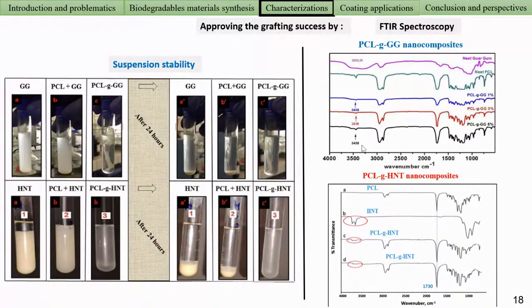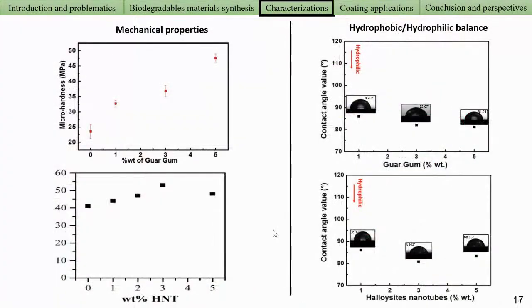And to confirm that we really grafted our polymer on the fillers, we studied the suspension stability of our nanocomposite in dichloromethane, and the mixture of free polymer and fillers in dichloromethane, and also fillers in dichloromethane. As you can see here, after a few hours, we observe the precipitation of fillers. And with our nanocomposite, we still have a stable suspension even after 24 hours. This indicates that we really grafted the polymer on the surface.